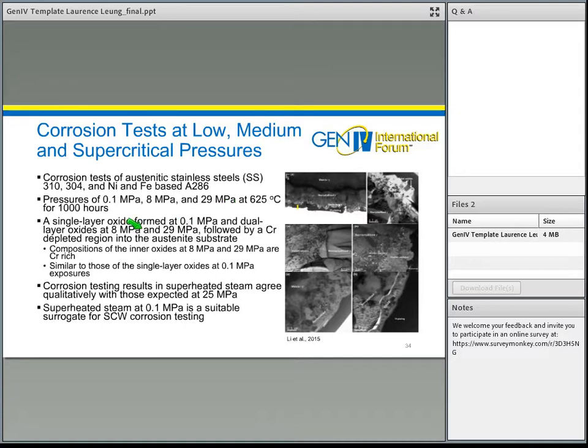What they found is a single layer oxide formed at low pressure, and a dual layer oxide formed at high pressure, 8 megapascal and 29 megapascal, followed by a chrome-depleted area into the substrate. But if you examine it closely, the composition of the inner oxide at 8 megapascal and 29 megapascal is also chrome-rich, and that layer is similar to the 0.1 megapascal low-pressure exposure. So based on the test results, they found that using superheated steam may provide qualitatively similar information to testing at 25 MPa.